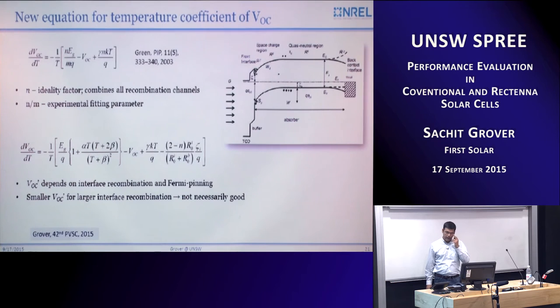Another thing that I worked on more recently and published in the PVSC this year is the temperature coefficient of the VOC itself. And we are all familiar with this well-known equation previously published in 2003 by Professor Green from this university. What I did was I essentially took the temperature derivative of the VOC in the equation that I showed before, and I get an equation which is similar but different. So here's the band gap term, which is very similar to what is in Green's equation, the VOC term, which is very similar, the gamma kT term. But then there emerges this other term, which is dependent, again, on the band bending that's happening in this device.